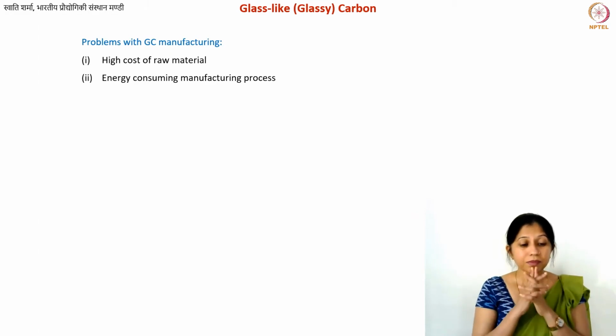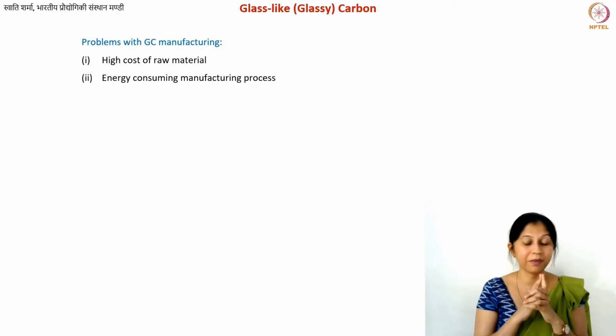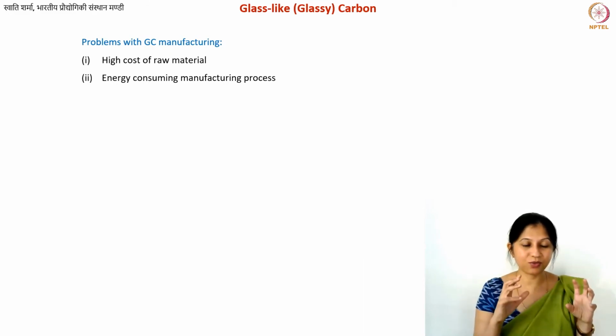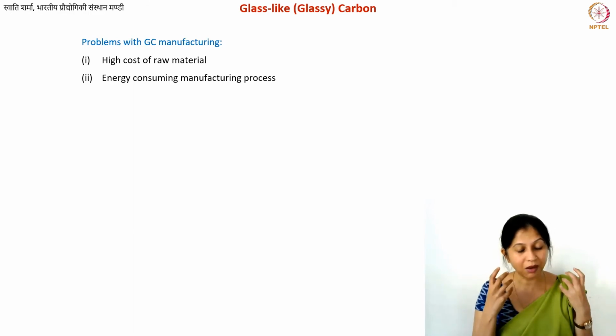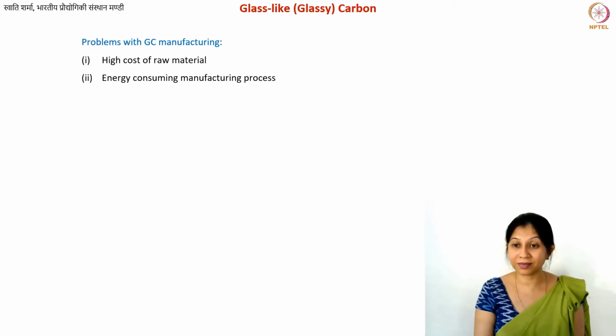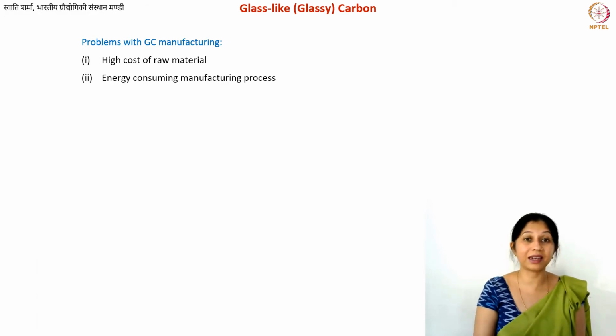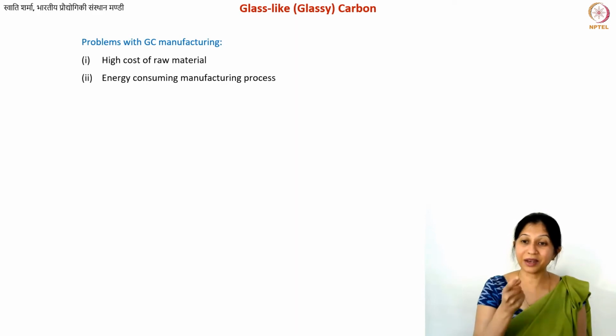Okay. Now, you are doing the heat treatment at 3000 degrees. That is also the case with synthetic graphite, by the way, or carbon fibers. Heat treatment temperatures are high, which means, just think about it, how much energy your furnace will consume. You need so much electricity to run your plant. You want to perform a certain process at 3000 degrees for prolonged durations. Also, the heat treatment sometimes is done in two steps. You heat something up to 1000 degrees, then you cool it down, you refill your resin or whatever, and then you heat it again up to 3000 degrees.